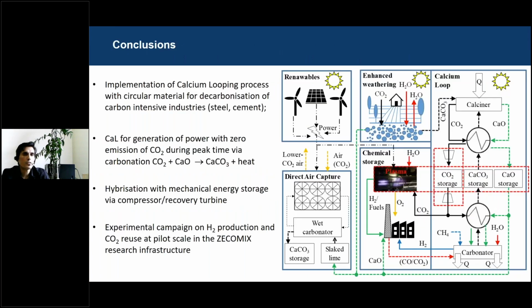So, to conclude, I would like to finish with a kind of graphical abstract. You can see that calcium looping is a very flexible process, because you can store excess energy. You can produce even hydrogen as a fuel, or as a reducing gas in steel mills, or for replacing methane or other conventional fuels. You can produce calcium oxide as raw material in cement, or also in steel mills. You can use the calcium oxide from the calciner in a slaked lime, just to assist also direct air capture.